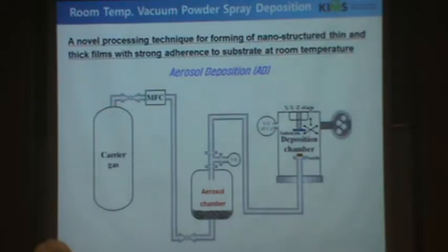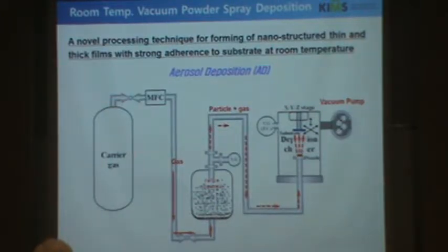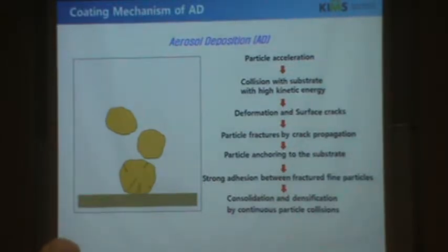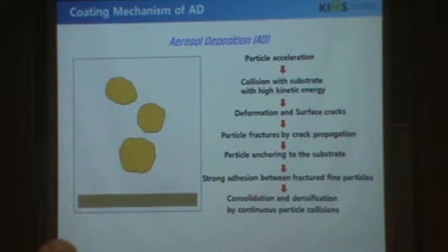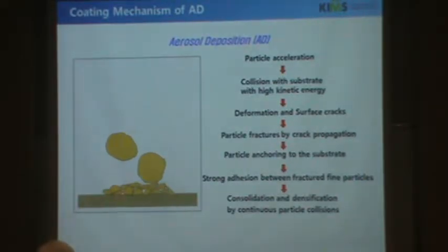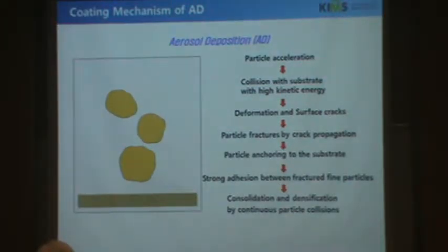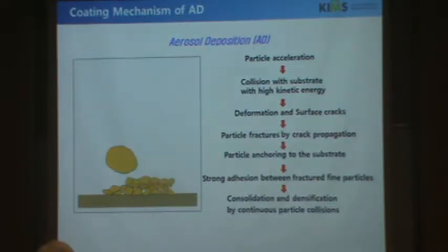This is the mechanism of coating. There's a vacuum and a carrier gas. The gas carries the powders and shoots the powder on top of the substrate. Seeing is believing one more time. Actually, we don't know in detail the exact mechanism of why it makes such a strong adhesion. But we guess: you can make a new, non-contaminated surface during coating. So we guess the new surface can make a very strong adhesion.